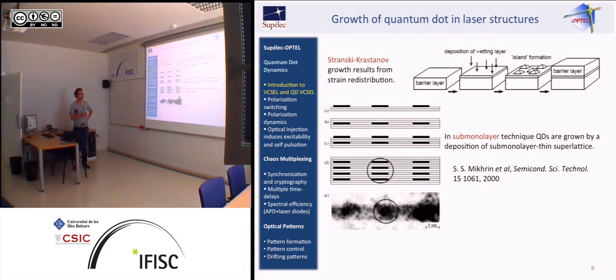Another technique, and I'm not that much a specialist in that, but another technique people told me about, and we have some devices on that, is that if you are growing superlattices, so very thin epitaxial layers, and you play on the thickness of the layer at the sub-monolayer level, you can also have spontaneous growth of quantum dots appearing on top of those sub-monolayer thin superlattices. So you end up with these black areas that in fact contain quite a large number of quantum dots. So you have those two techniques for growing these things, the Stranski-Krastanov and the sub-monolayer techniques.